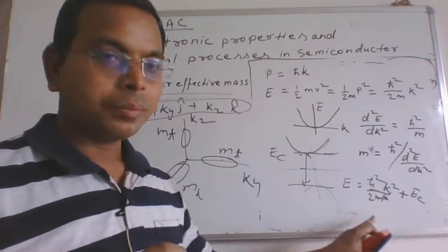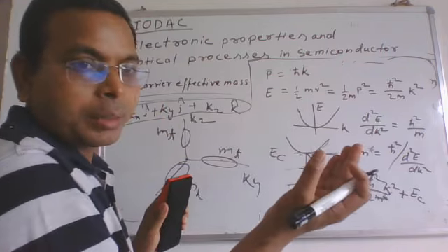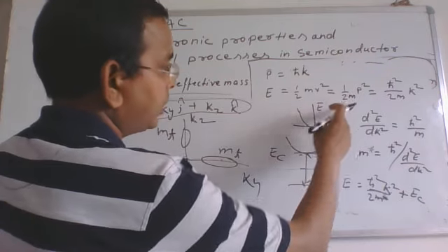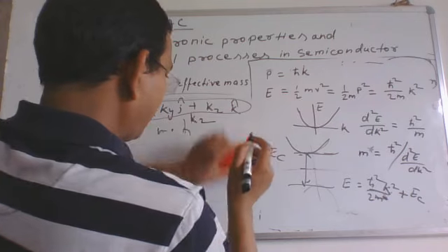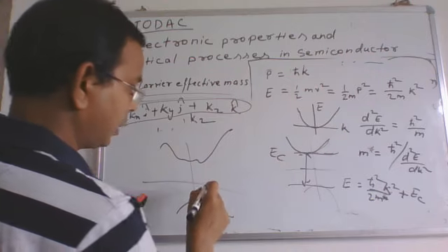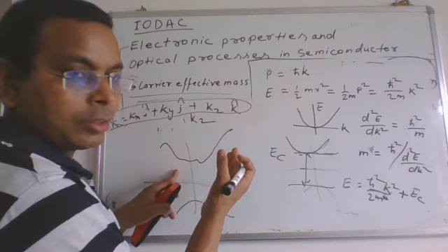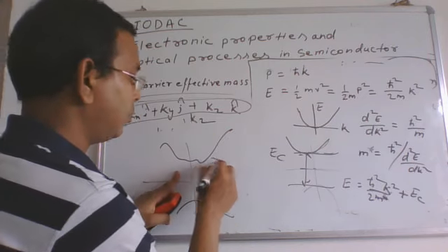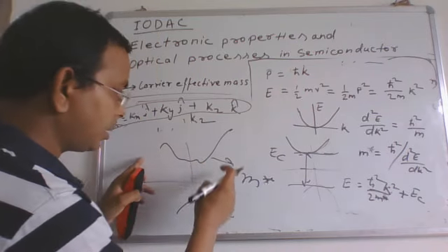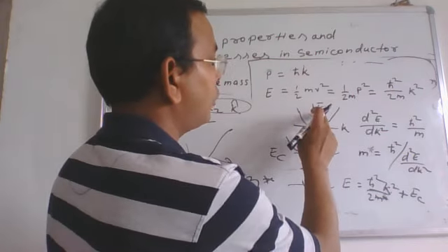So effective mass gives us this quadratic pattern. If we don't take this, and if we take separate masses for the longitudinal direction and transverse direction, this will not look quadratic. So the actual E-k diagram may be like this, but to deal with it perfectly with good equations, we model it with the effective mass m star. When we replace all the masses with the effective mass m star, then we can take the quadratic dependency of E with respect to k.